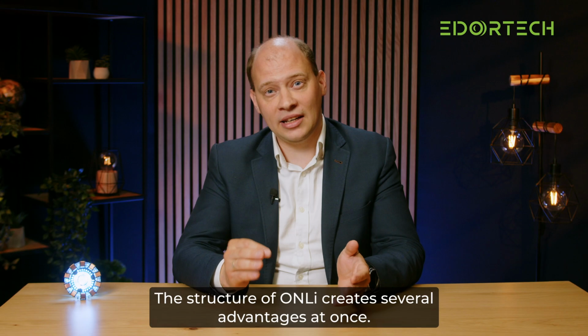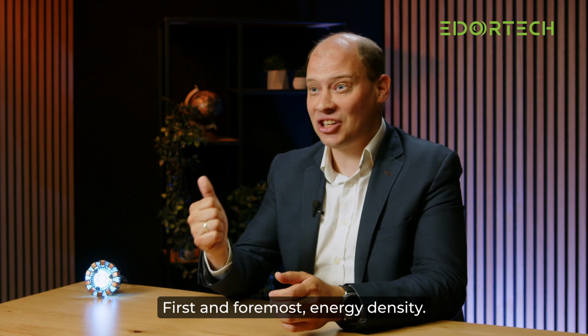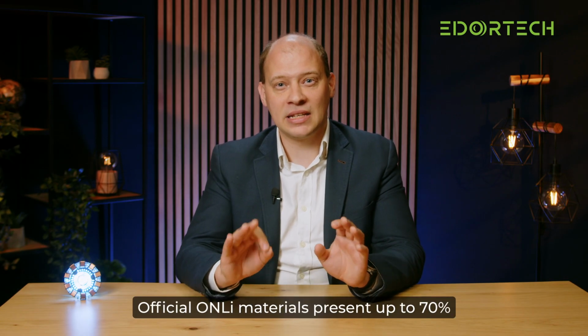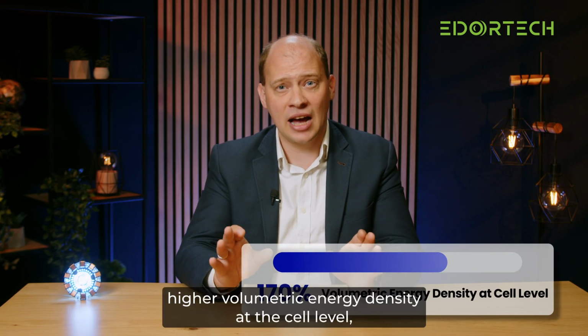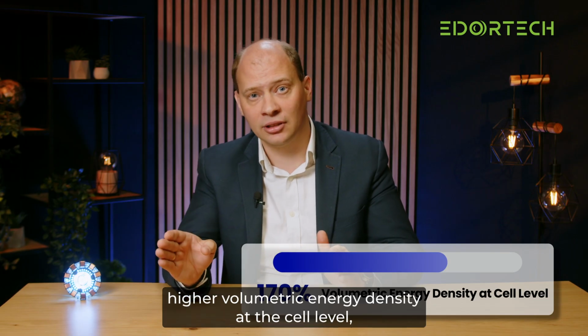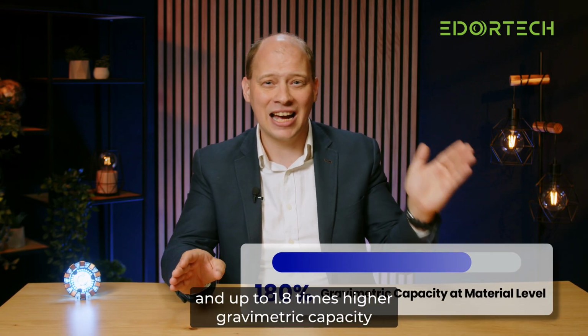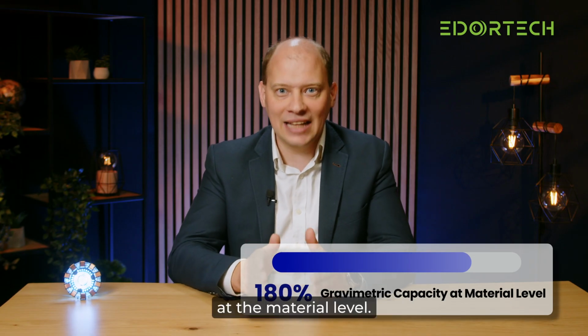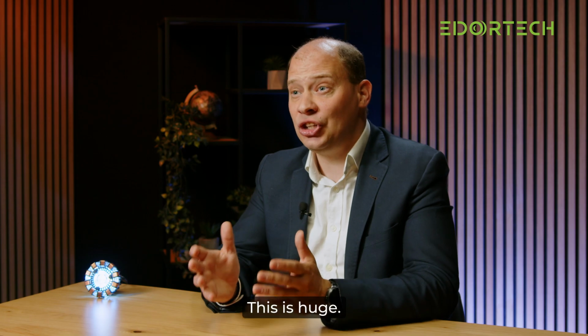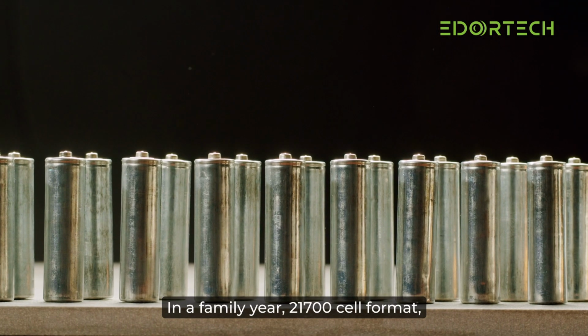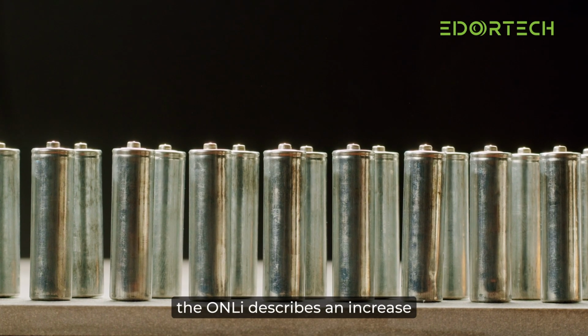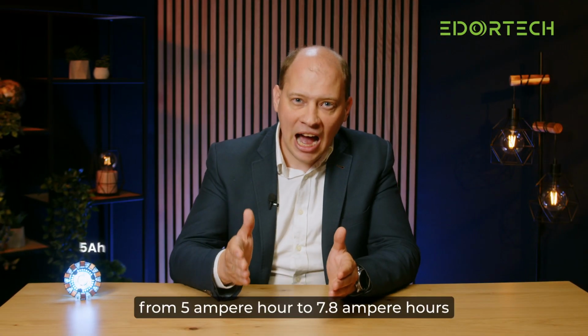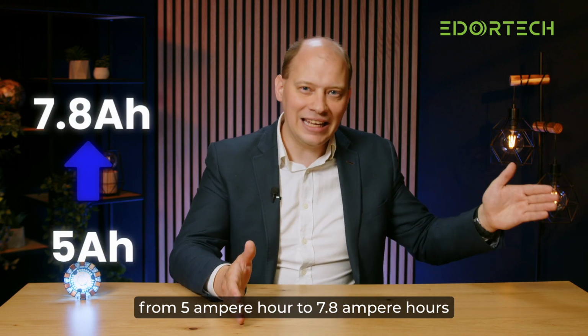The structure of ONLi creates several advantages at once. First and foremost, energy density. Official ONLi materials present up to 70% higher volumetric energy density at the cell level, and up to 1.8 times higher gravimetric capacity at the material level. This is huge. In a familiar 21700 cell format, ONLi describes an increase from 5 ampere-hours to 7.8 ampere-hours in exactly the same format.